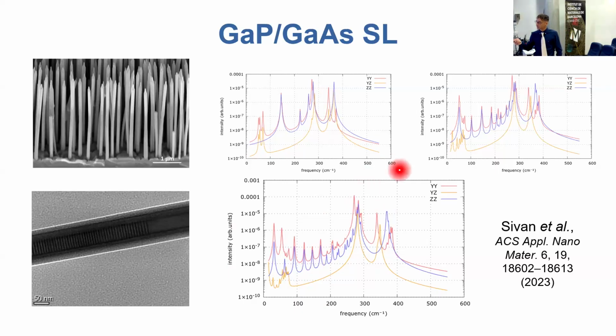And this is particularly interesting because it is the proof that superlattices can be used as a viable means of engineering the phonon spectra of the material, and then also to tune and control their optical and thermal transport properties, because, as I said before, the phonons are the particles carrying energy in these structures.